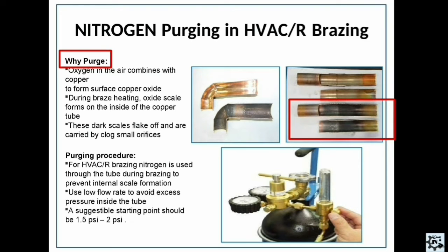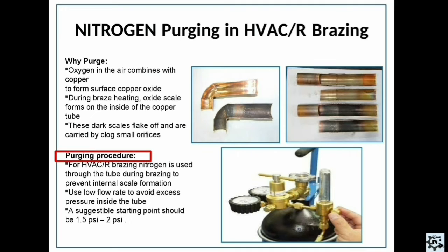For preventing such issues, we need to follow the nitrogen purging process during the brazing operation. Now what is actually the procedure for the nitrogen purging process? Here nitrogen is passed through the tube during brazing to prevent internal scale formation. But one thing we need to take care of is to use a low flow rate of nitrogen during the nitrogen purging process, because if we use a high flow rate of nitrogen, then the excess pressure inside the tube restricts the flow of brazing material during the brazing operation, so it may have an adverse effect on our brazing quality. The suggested pressure of nitrogen used during the nitrogen purging process is 1.5 psi to 2 psi, for preventing excess pressure issues during the brazing operation.